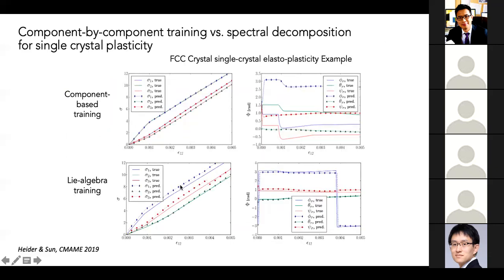One thing that I want to test is that we also have material data that can have a change of orientation very quickly, in this case crystal plasticity. If we train it component by component, this is what's going to happen. Because the data is crystal plasticity data, it can have a slip system getting activated, and what you can see is that you may lose the slip because the parameterization in the component-based training is not very sensitive to the onset of a sudden slip system, of a sudden rotation in your tensor. But the Lie algebra allows you to capture the slip system activations.